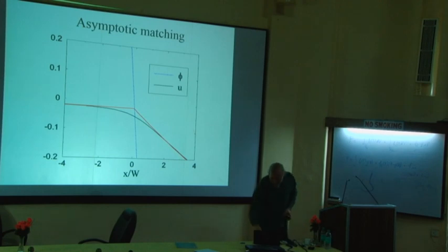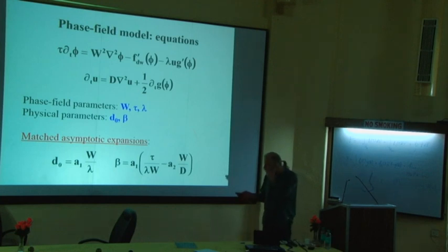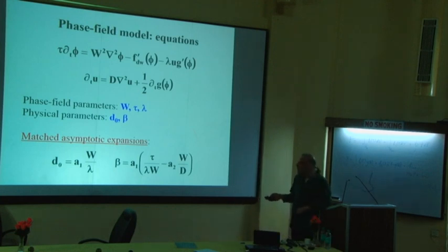Okay? So just to come back to these formulas that you obtained, there's one very important point. This here is the expression for the capillary length. So in some sense, this is a sort of strange way of writing the Gibbs-Thomson condition, because the capillary length contains the surface tension, okay? And this relation is actually quite easy to obtain. You can obtain it by the type of simple calculations that I have done with you for the Cahn-Hilliard equation and for the Allen-Cahn equation. That's not much of a problem.